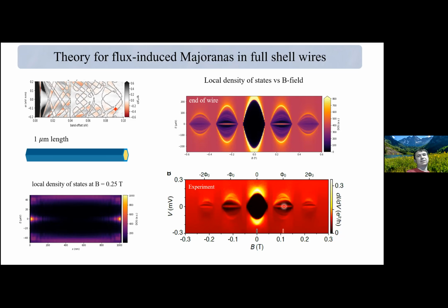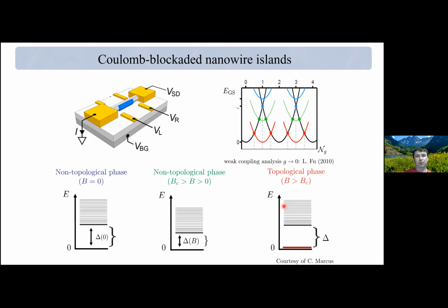So of course, this is again in the class of zero energy states. So we want to take the next step forward and show whether we have the expected scaling of the energy splitting between zero energy states due to finite size effects. And in order to do so, experimentalists devised this very clever experiment where they used Coulomb blockaded islands. So these islands are now floating rather than grounded. When you have a floating island, there's Coulomb energy that one has to pay in order to add an extra electron to the system.